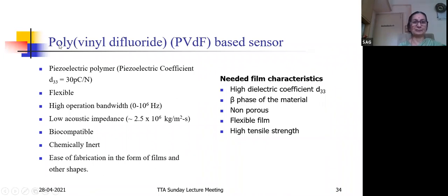We selected polyvinylidene fluoride for this particular material because it has a piezoelectric coefficient of about 30 picocoulomb per Newton. It is flexible. It has a high operation bandwidth, right from 0 to 10⁶. It has low acoustic impedance, which we were requiring. It is biocompatible. If you put it on the human hand, biocompatibility is also to be seen, otherwise the person will get irritated. And it's a chemically inert material, and it is easy to fabricate in the form of films and other shapes. Therefore, we selected this.